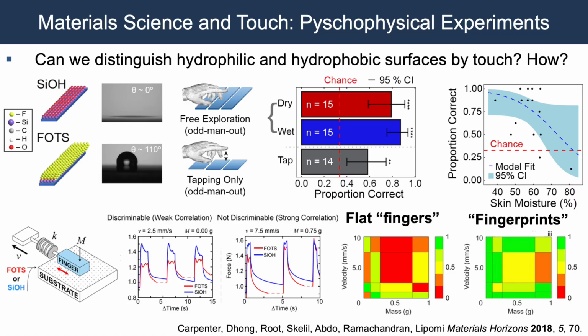We were very interested then in how we could use materials characterization techniques in order to understand why we were able to distinguish one surface from another. So my postdoc Charles Dong built this surface force apparatus with a silicone finger dragged across a substrate that differed on the basis of surface chemistry, and he took these tangential friction traces at different levels of scanning velocity and downward mass, and found that at some combinations of scanning velocity and downward mass, we got identical or very well correlated tangential friction traces. So these are very well correlated. These would be very difficult to distinguish based on this scanning velocity and this downward force.